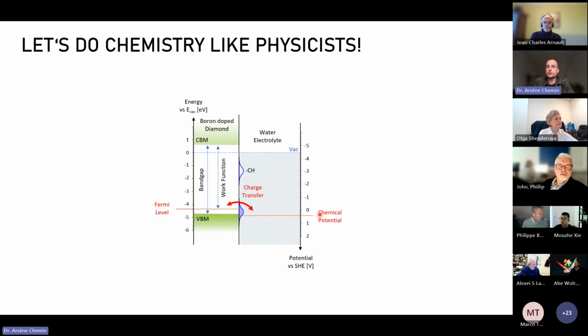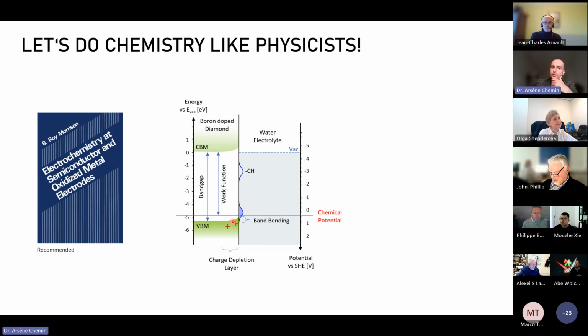When you put those two worlds together, you can see there is a mismatch between the Fermi level of the diamond and the chemical potential of the environment. And this mismatch will lead to some electrons of the diamond, in that case, to jump into the surrounding electrolyte. I can only recommend this book if you're interested in semiconductor electrodes, which is a very good book. And this charge depletion layer here will create surface band bending of the diamond.